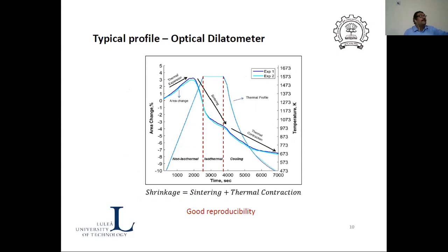And this is what, so though it is a heating microscope, we call it an optical dilatometer. So we have published at least 3 articles in Metallurgical Transactions on this particular methodology. So if you look at this, this is one of the temperature profiles which we used. There's a heating rate, then we maintain it at somewhere close to 1573 K, 1300 degrees Celsius, and then we cool it. Okay, and during that time the pellet expands because of thermal expansion, and then you can see that it starts shrinking because of sintering.